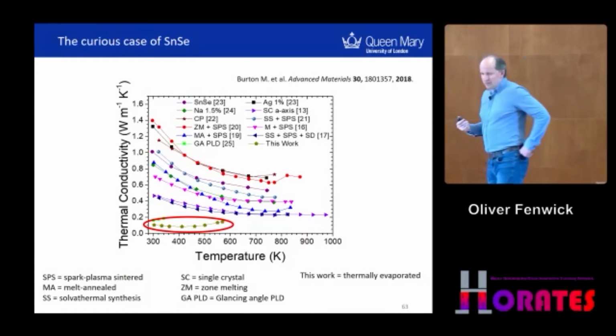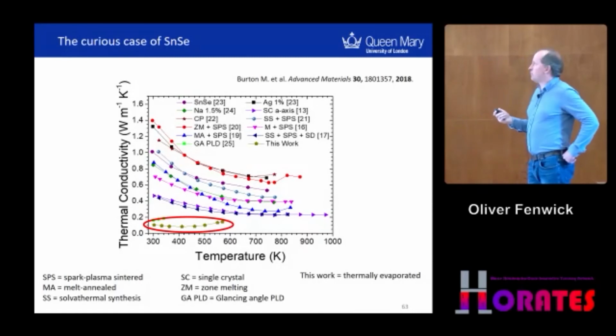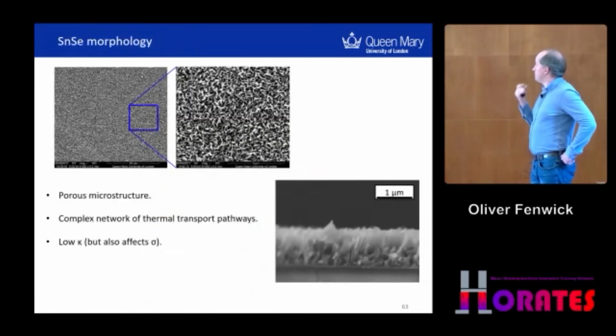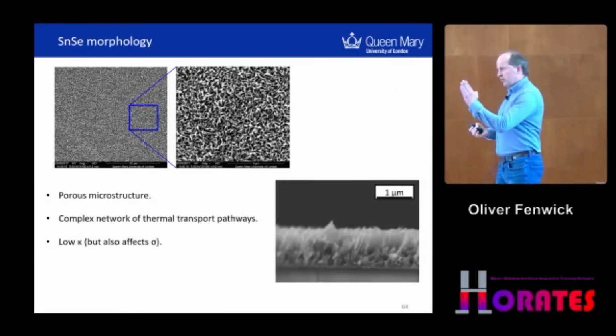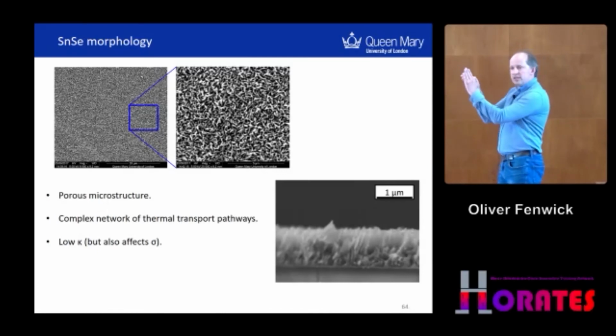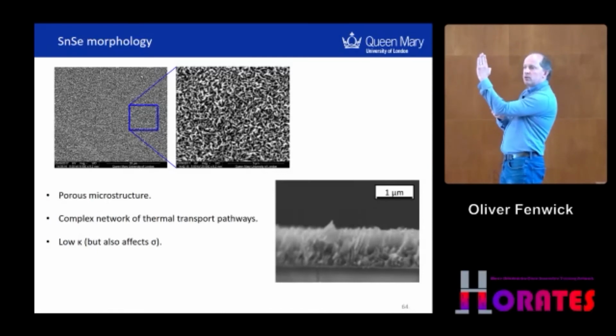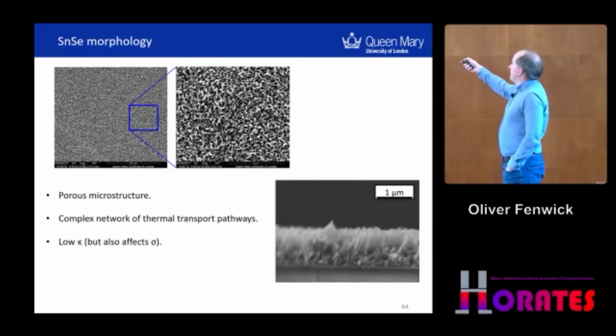And so I told my students to go and look at this sample in more detail to find out what's going on. And when we put it in the SEM, we saw this. We saw that the film was made up of thin sheets of tin selenide pointing up off the surface, and they form a very porous structure.